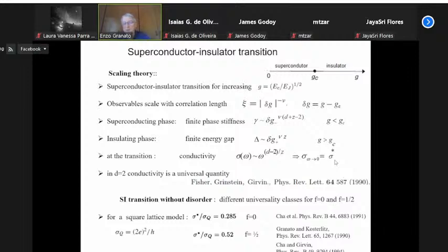This quantity has been measured experimentally and also obtained both analytically and by numerical simulation. For the superconducting array, it's maybe not surprising that the results depend on the frustration, and as shown here, they are different. For frustration equal to 0, there is zero magnetic field, while f equal to 1/2 corresponds to a magnetic field of one flux quantum per two cells. On a square lattice, this conductivity in units of the quantum conductivity for a Cooper pair has this value, obtained numerically and analytically. And for f equal to 1/2, the result is different. You see it's almost twice the value for the zero field case. And these have been shown analytically and numerically.